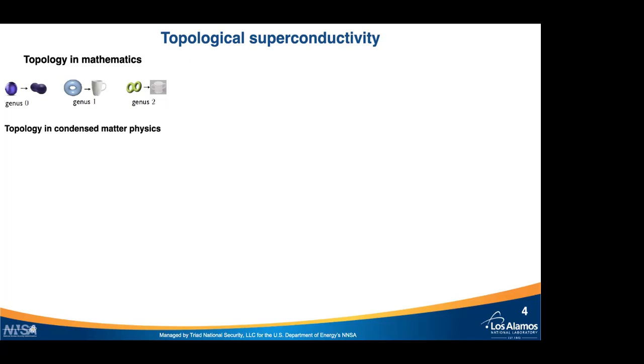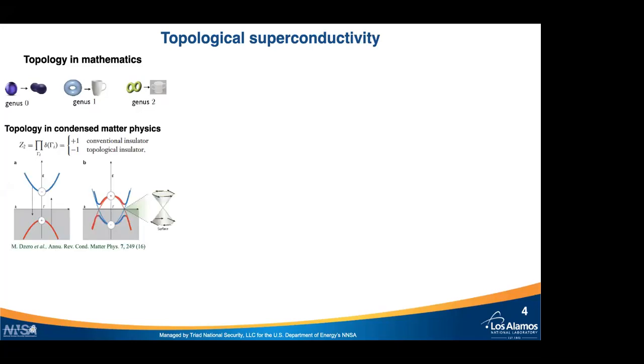But more recently, this concept was also extended to condensed matter physics. And here, how can we think of this difference? Well, we have to look at the band structure of the material. In one of the simplest examples, when you have a system with inversion symmetry, you can calculate the so-called Z2 topological index, which is a product of the parities at high symmetry points. Looking at the figure on the left, we have a simple, conventional or trivial insulator where this product will be +1. On the right side, when you have inversion symmetry driven by spin-orbit coupling, then this product of parities will be -1, and you have a topological insulator. And this state is very interesting because it means that one has to have surface states that are protected by time reversal symmetry in this case.